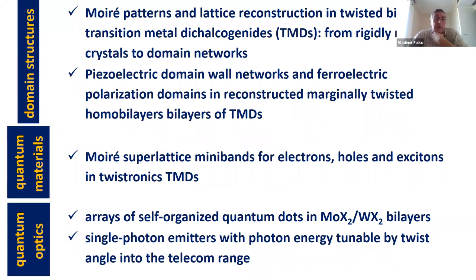And just to summarize what I was talking about, there is an interesting system where self-organization of the lattice allows us to get arrays of quantum dots with strong localization of charge carriers. For homobilayers, these would be separate places across the Moiré structure where electrons and holes would be localized, and we have all the information about where the band edges are across the Moiré superlattice as a function of the angle, and a quantitative description of the corresponding quantum dot potentials. And for heterobilayers with the same chalcogen, we get really strong self-organized quantum dots localizing both electrons and holes in the same place, and therefore getting strongly localized excitons.